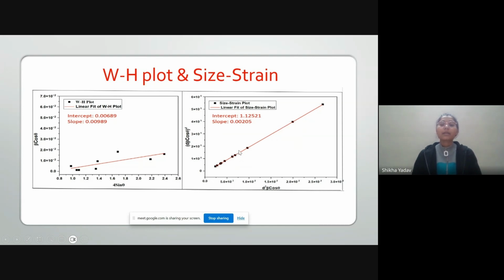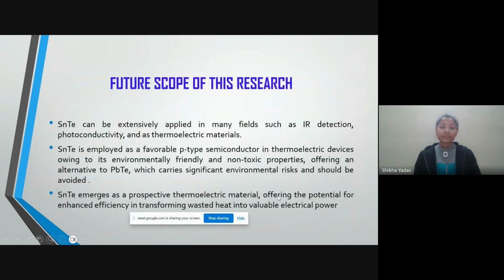Similarly, I used the third method, the size strain method, and using this plot, we were able to calculate the crystallite size and the strain. The values that I obtained were: for the Debye-Scherrer method, the crystallite size was 63.14 nanometers. When I used the WH plot, the crystallite size was 20.1 nanometers, and this much strain was observed. For the size strain method, I got 67.8 nanometers, and this much strain was observed.